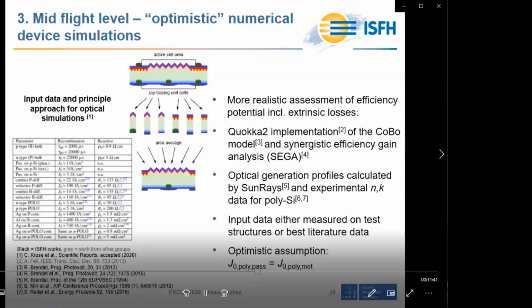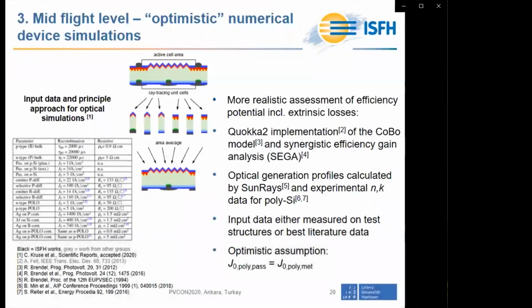To get a realistic assessment of the efficiency potential of this specific combination of an electron-collecting polysilicon oxide junction and a hole-collecting P+ region, we perform numerical device simulations to include all relevant extrinsic losses. We use the Quokka 2 implementation of the conductive boundary model and combine it with a synergistic efficiency gain analysis. The optical generation profiles are calculated by the ray tracing software SunRays by using experimental n-k data for each layer, in particular also for the polysilicon. And the input data for the numerical device simulations are listed here in this table.